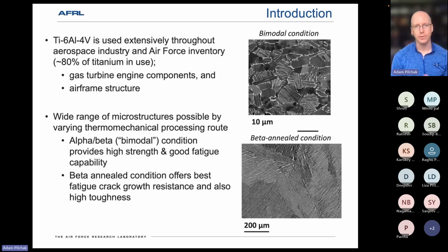There's a huge range of accessible microstructures depending on the processing routes. So temperatures you deform at, the strain paths you apply to work the metal, and then the subsequent cooling rates from those and/or solution heat treats as necessary. Among this myriad of microstructures, there's two that are kind of the most common. So in the upper right there, we're looking at the bimodal microstructure, where you've got a mixture of these, excuse me, equiaxed alpha particles, and then they're set in a matrix of what's often called transform beta. So it's a mixture of alternating alpha and beta laths.